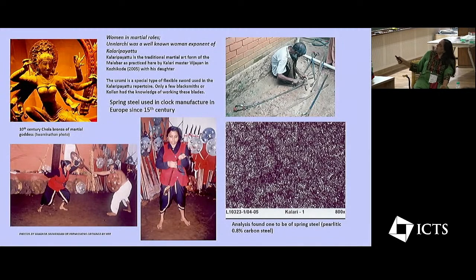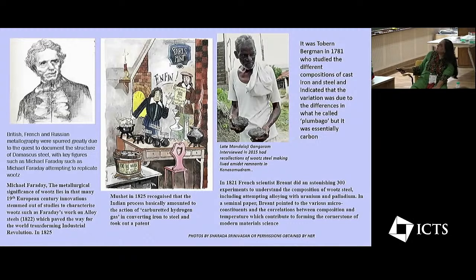Another interesting aspect, because I would like to keep the emphasis on women, I was quite struck by, if you've been to Kerala, the Kalari Payattu tradition, where you have this blade which coils up like that and then uncoils, and so you can use it. It's quite swashbuckling to watch, and this is a practitioner here. I found this quite interesting because it's actually made of spring steel, which had about 0.8% carbon in it. So not all the steels were the same; they had specific kinds of steels that they were using for specific purposes. And this is what we call spring steel. We know that spring steel came into vogue in Europe for clock manufacture and so on by the 15th century. But here is an example of the use of spring steel in a different context, maybe less functional. Now, I think I just have another 2-3 more slides before I finish.